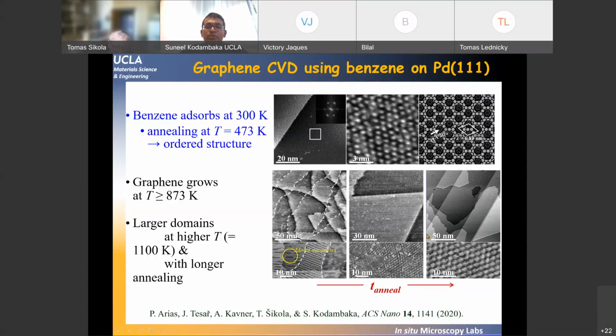And so we were able to show that you can have an adsorbed layer of benzene that does not form graphene until you heat it up to fairly high temperatures, which is in contrast to what has been reported for graphene formation using benzene on copper surfaces, which seems to happen at fairly low temperatures. Okay, so that's what I wanted to show you for graphene growth.